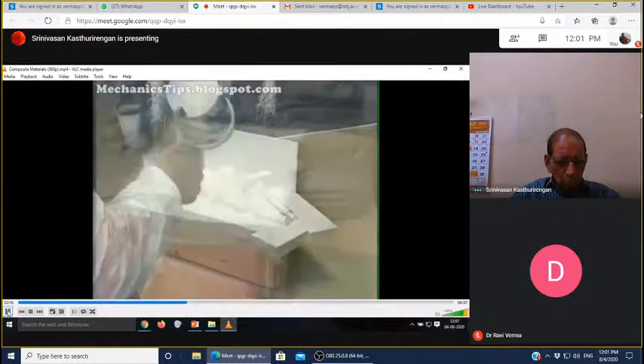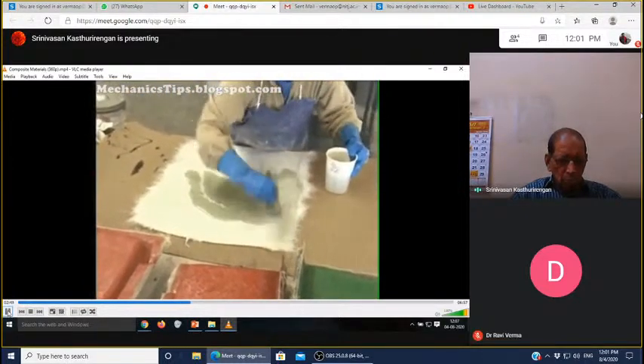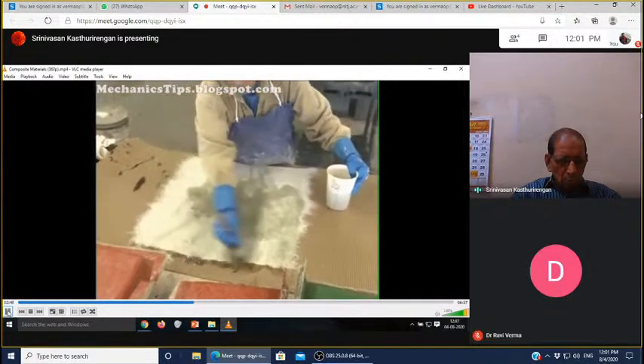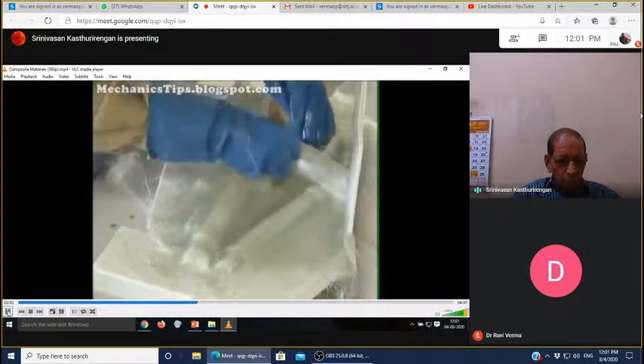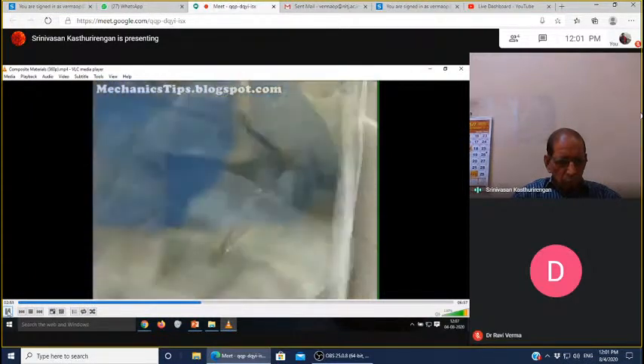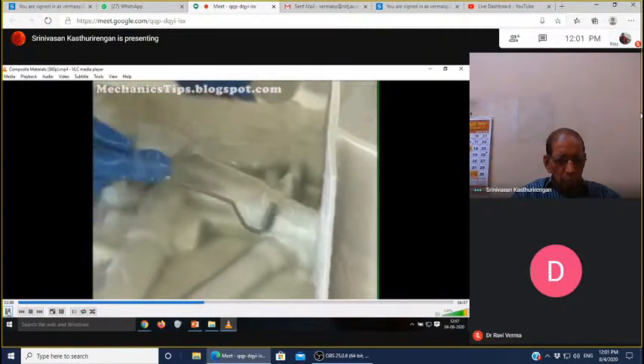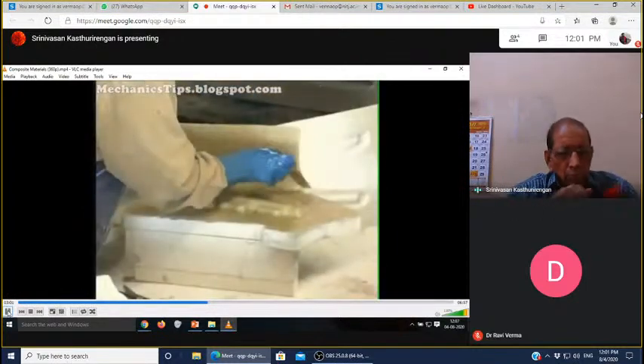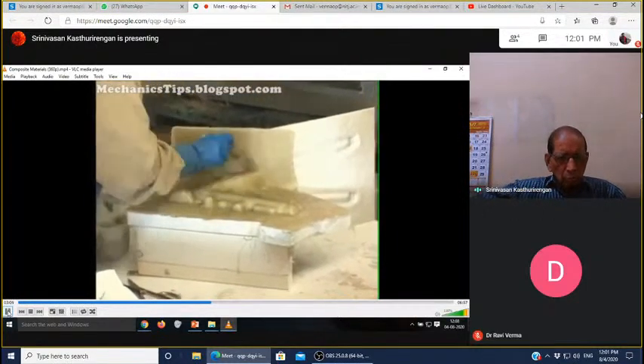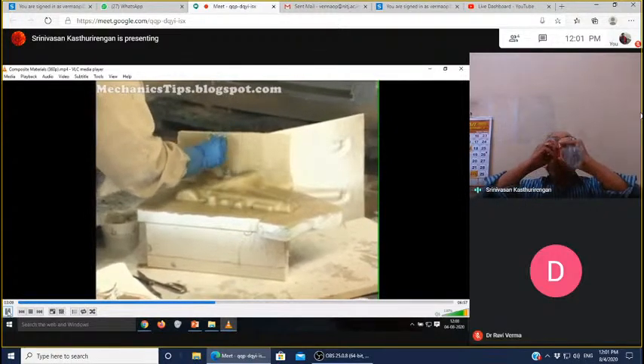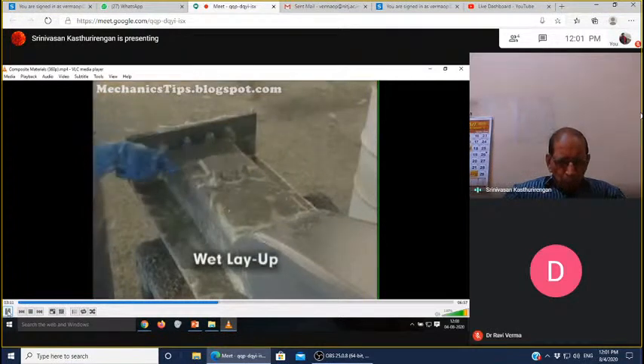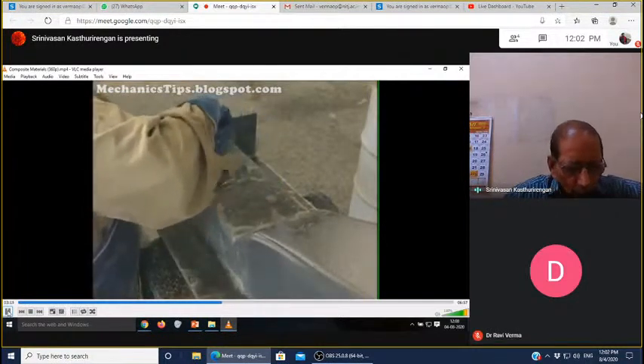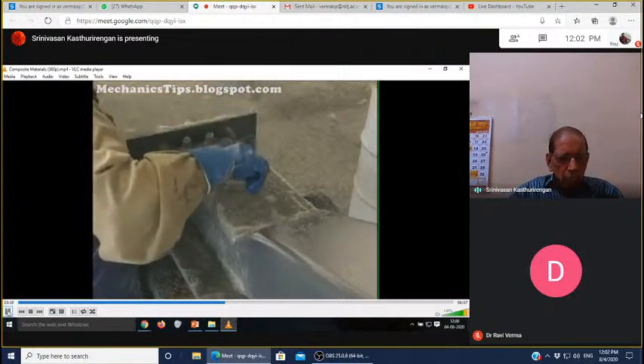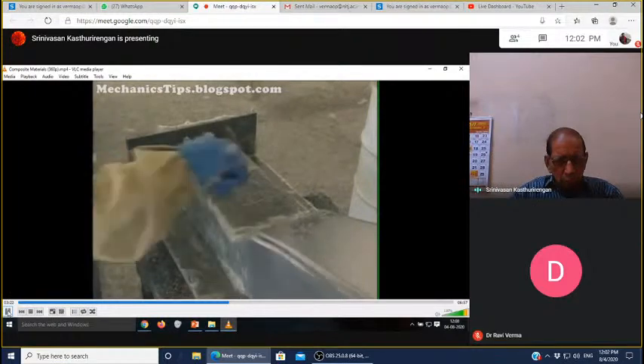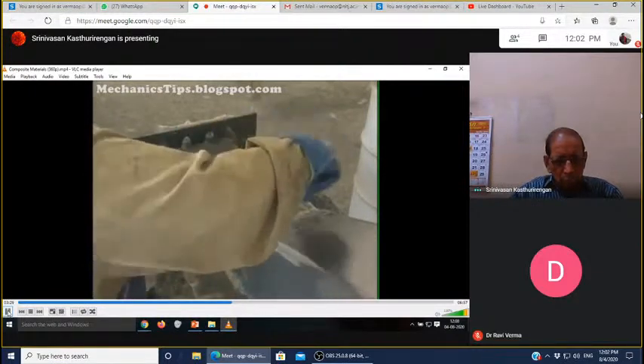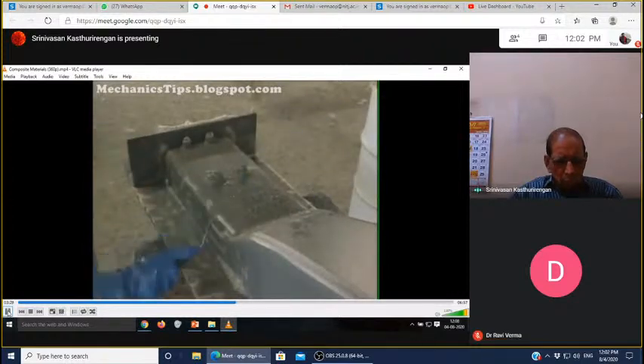As the gel coat cures, the reinforcement material is prepared for application by impregnation with wet resin or matrix material. The impregnated reinforcement material is then placed on the coated mold surface and hand-rolled for uniform distribution and removal of entrapped air. More reinforcement material and resin are applied as needed in this manner until required part thickness has been built up. This so-called wet layup method can be used with nearly all reinforcement materials and is widely used to produce glass-reinforced polyester products and sometimes glass-reinforced epoxy products. Wet layup is also used for making composite molds.